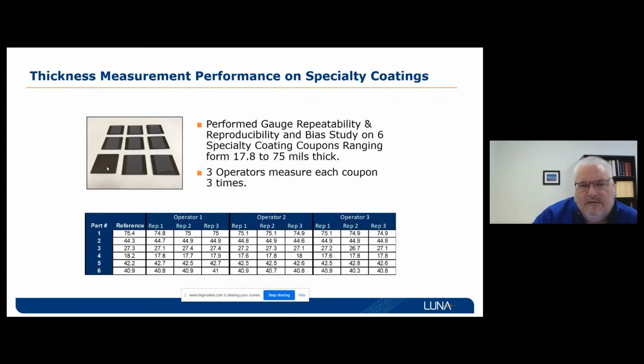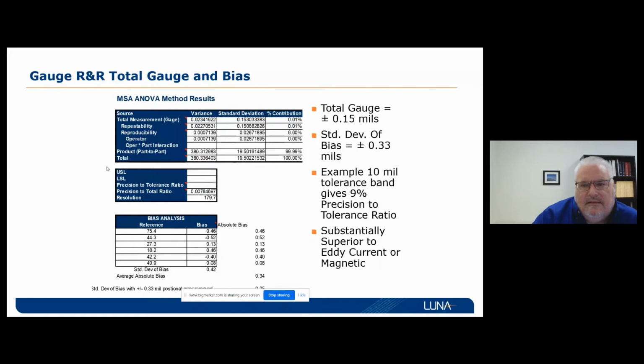This is just a specialty coating measurement, doing a gauge R&R, where we have 3 operators measuring each coupon 3 times with a handheld system. This gave, for example, a 10 mil tolerance band with a 9% precision to tolerance ratio, with the total gauge of plus or minus 0.15 mils. Again, for those used to American units, we still use thousandths of an inch instead of microns. 1 mil is 25.4 microns.